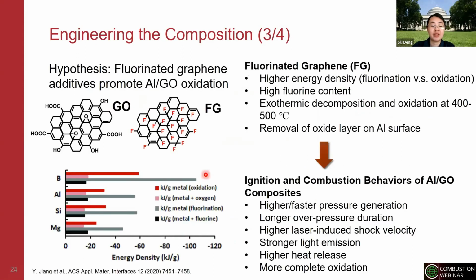And further, we were thinking, okay, the 2D materials work, the graphene oxide works. How can we bring some of the fluorinated additives into the system, and whether we will achieve any synergistic effects from that. And the reason why we're interested in the fluorination, as I mentioned previously, is first of all, it can remove the oxide layers of aluminum, and it can prohibit the agglomeration of the products. And another reason demonstrated here is that in general, the fluorination, compared to the oxidation, will release more heat.